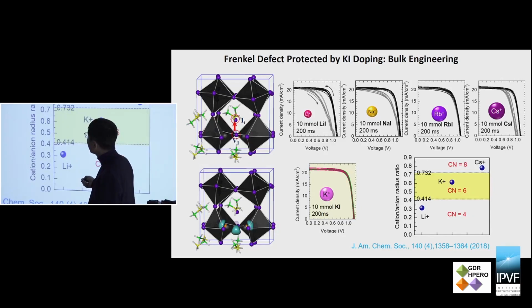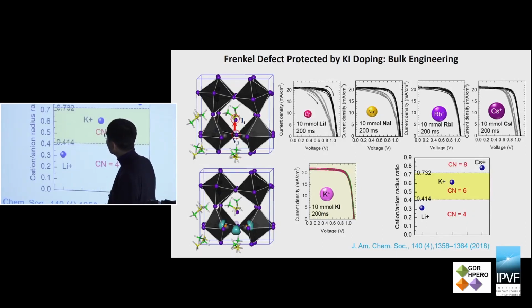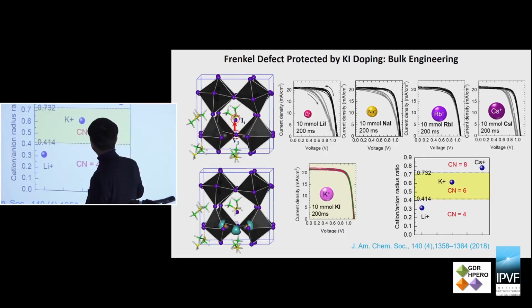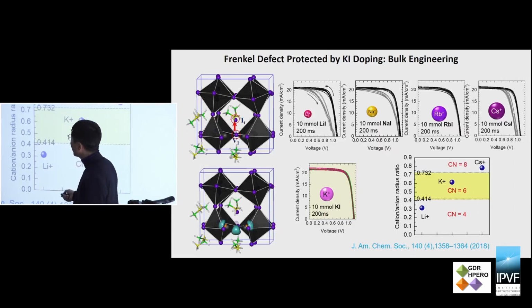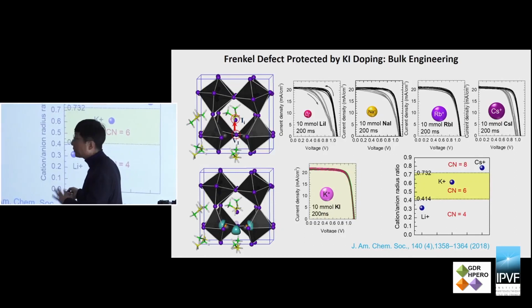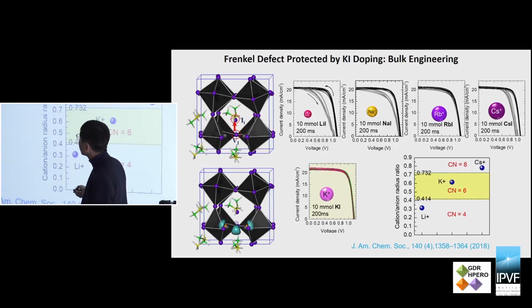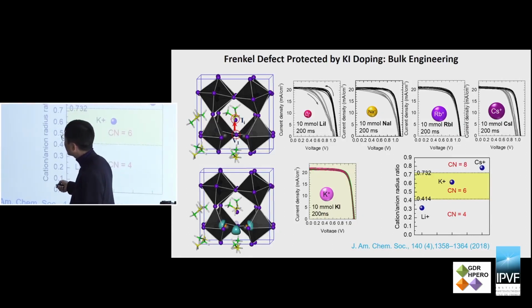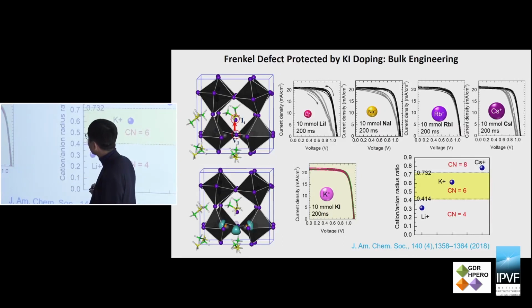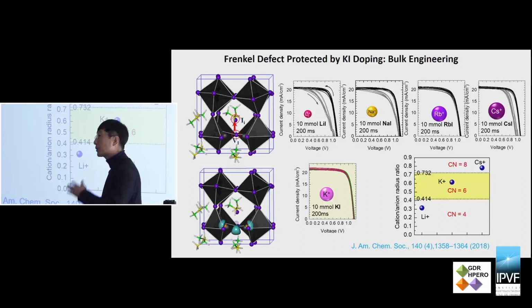So we actually added, this is not millimole, this is micromole, a very tiny amount of alkali iodide, such as lithium, sodium, rubidium, potassium and cesium. Then we found that potassium iodide gives almost no IV hysteresis. However, lithium iodide, and even the larger cesium iodide, still gives very severe IV hysteresis. From this result, we calculated using DFT, and probably the defect is related to the Frenkel defect. A Frenkel defect means that the corner-sharing iodide is moving toward an interstitial site of the A-site cation. So if you block this Frenkel defect by inserting the proper cation in this interstitial site, then you can protect against the Frenkel defect.